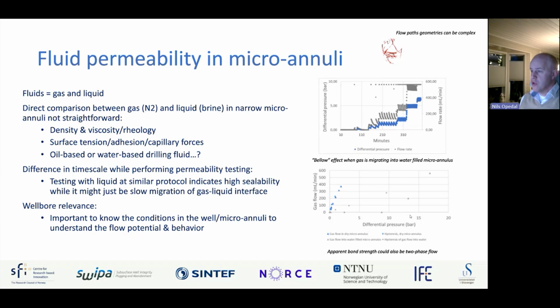The bottom right graph shows two sets of tests. One is with a dry sample and gas flow, where, as you increase the differential pressure, the gas flow increases linearly. Same thing when you do the hysteresis test going down again: it follows more or less the same line. However, if you do the same test on a water-filled microannulus, you see an apparent breakthrough of measured gas flow at about 8.5 bars. But when you do the hysteresis test, it does not follow the same line.